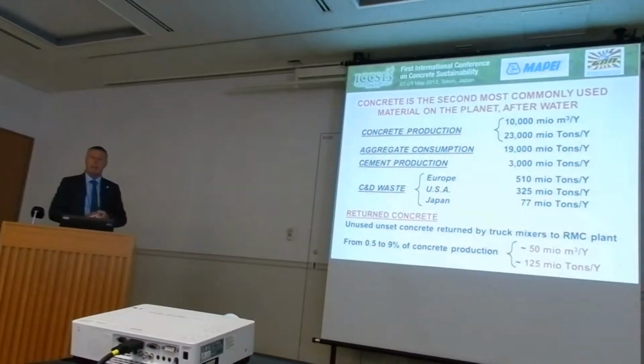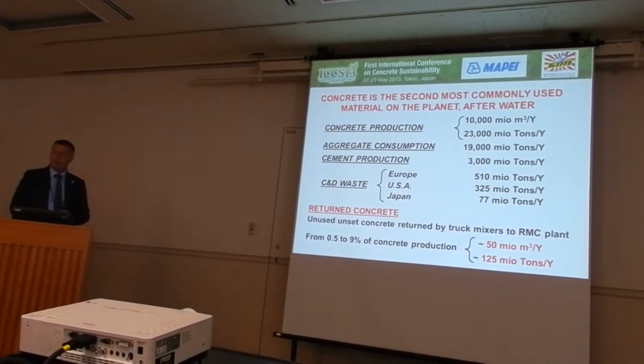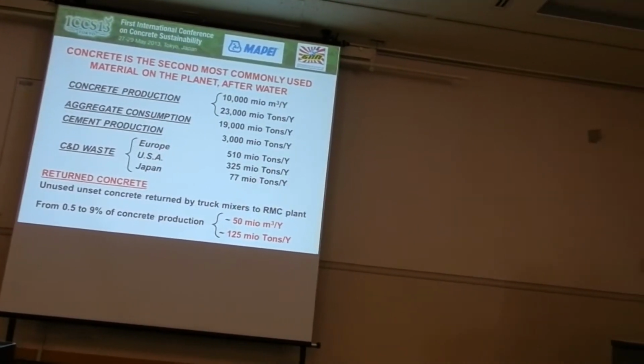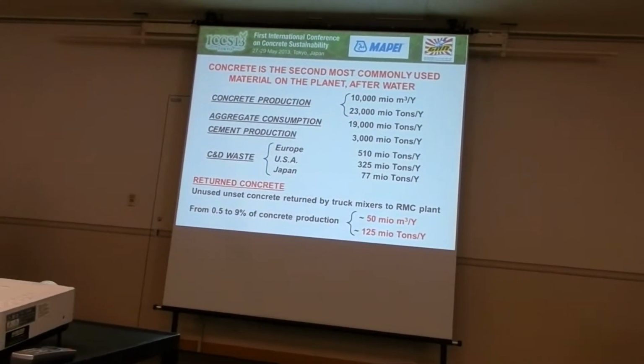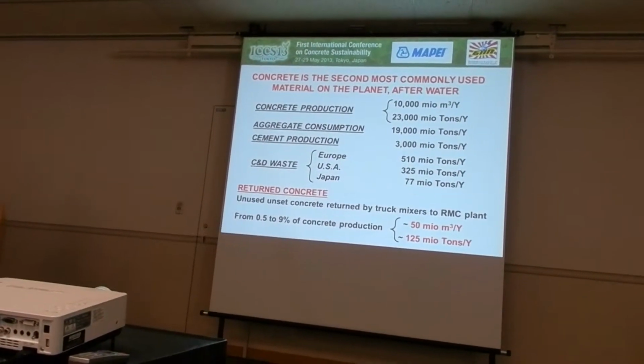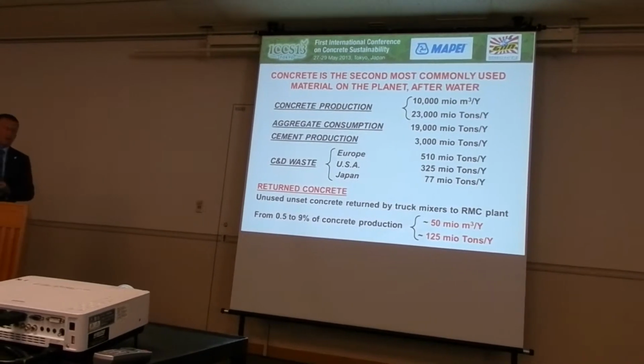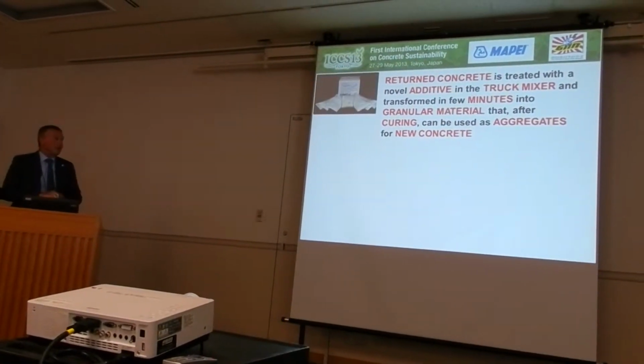Returnable concrete is the unset, unused concrete which is returned by the truck mixer from the job site, that for any reason is not placed and comes back to the ready-mix plant. And in many cases, this material can be a waste with many impacts from an environmental and economical point of view. In a conservative estimation, the global amount of returnable concrete is above 100 million tons per year. That means more than double the amount of the total concrete production in Italy.